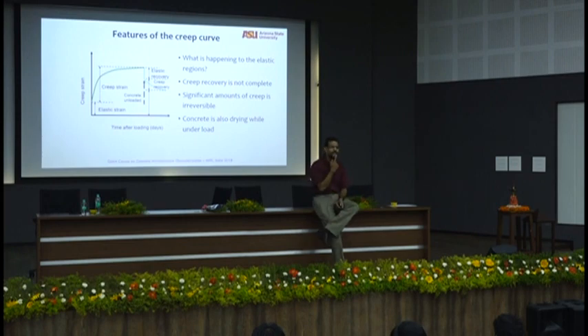Like you talk about statistics, right? You can say that a century in 50 balls is really good, or you can say a century in 50 balls is such rash batting, right? You can do both ways. So statistics can go both ways. Overall elastic modulus is lower, but what lowered the overall elastic modulus was the presence of these soft aggregates, which does nothing to creep of the cement paste, which is where the actual creep mechanism is happening.